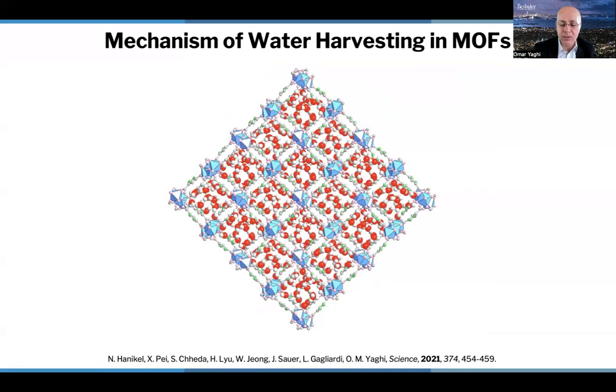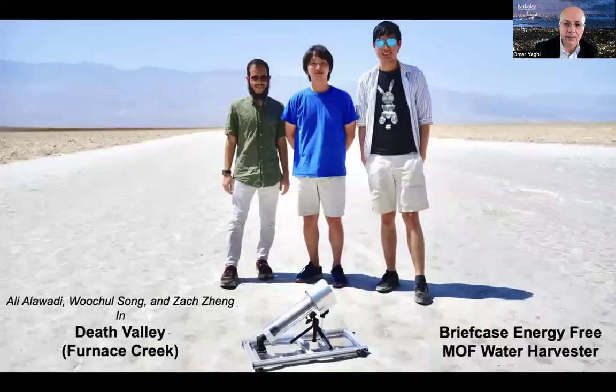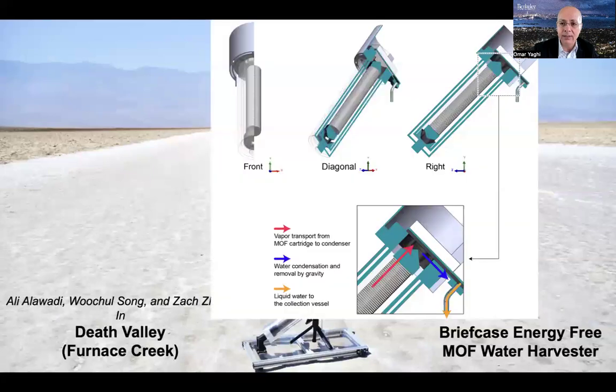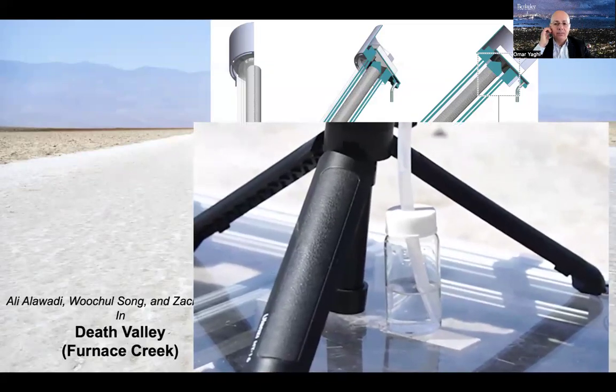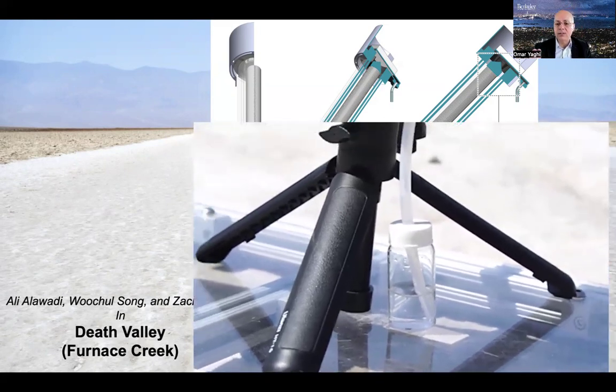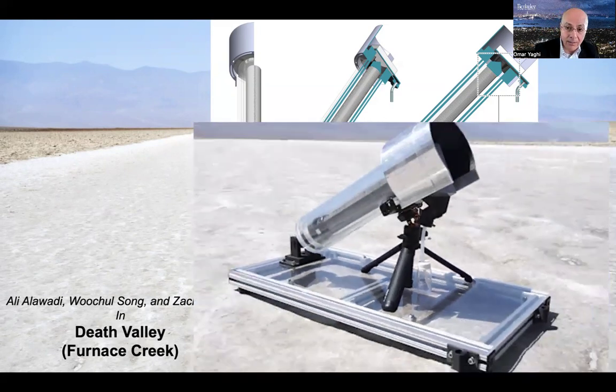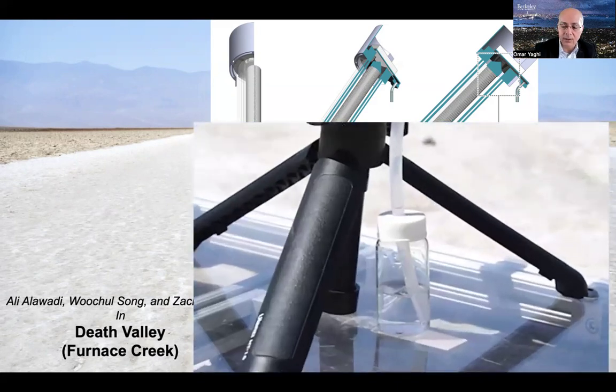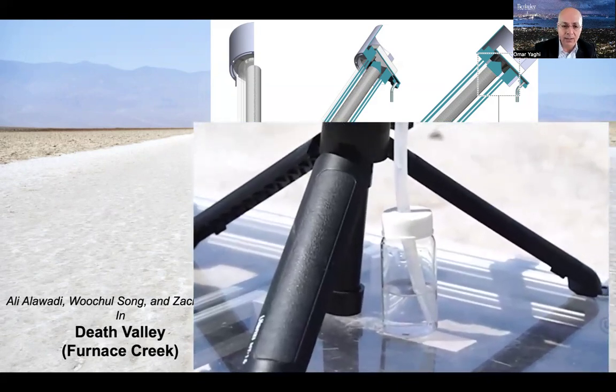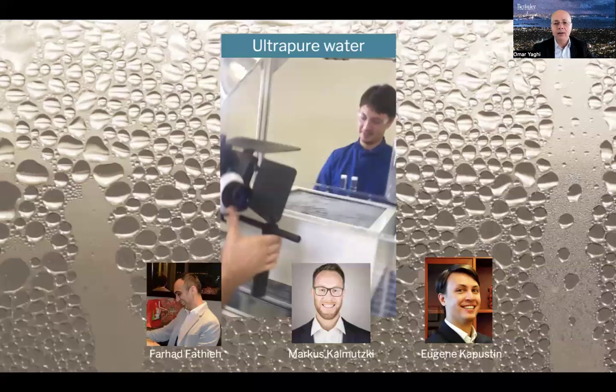So just by exposing the material to sunlight in a closed system, you're able to take the water out, as these students have demonstrated by making a device that they tested in Death Valley. Here's a device that's made from pancakes of MOF. During the night, the MOF is exposed to air. During the day, the device is closed down, it heats up, and then water comes out. This is just a demonstration of how powerful the MOF is in taking water out of even the most arid air.